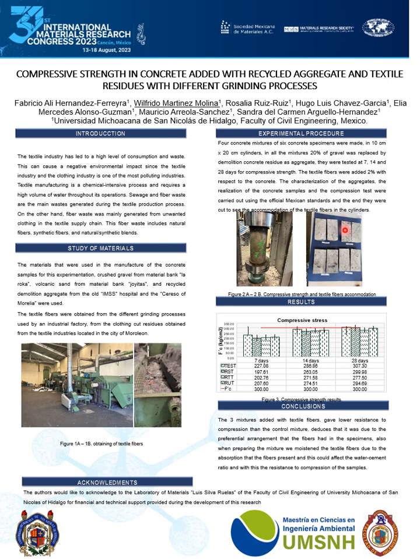We can see in this image the preferential accommodation in certain parts that the textile fibers had in the concrete specimens. The results indicate that only the control sample complied with the compression design strength, but the other mixtures reached around 90% of the design strength at 28 days. The 3 mixtures added with textile fiber have lower resistance to compression than the control mixture.